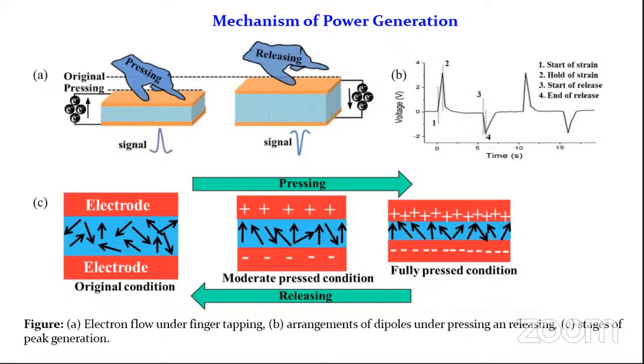So what is actually happening inside the crystal? You can see here the pictorial representation. The black arrows are representing the dipoles inside the material. In the original condition, those dipoles are randomly oriented inside the crystal. When we are pressing, those dipoles get oriented in a single direction. This is because of the stress induced polarization effect. When the material undergoes fully pressed conditions, a maximum piezo potential is developed on the respective surfaces. Because of that, we are getting maximum voltage and current at fully pressed conditions.